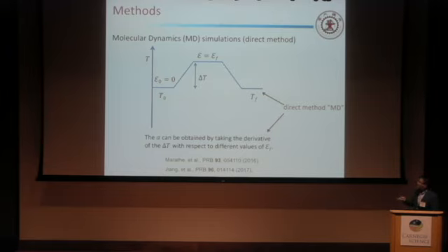The second is the molecular dynamics simulation, the direct method. Here, we first choose the initial temperature, then ramp the electric field up from epsilon to EF. Then we can get the delta T change. Then we can calculate the alpha. Alpha is the EC coefficient, which can be obtained by taking the derivative of delta T with respect to different values of EF. This method we call MD. This is a direct method.